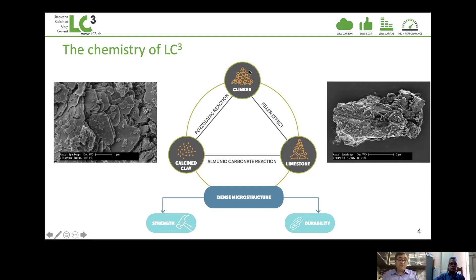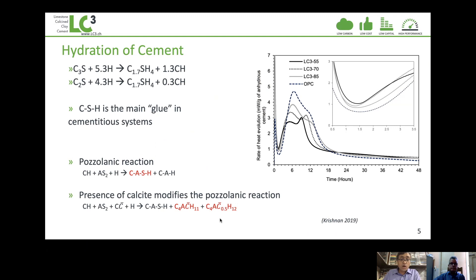This is despite having a lower clinker content. Whereas a Portland cement would have 90 to 95 percent clinker, and a fly ash-based pozzolanic cement would have 60 to 70 percent clinker, LC3 may have 50 percent or even less clinker and still achieve the same type of strength as other cements, at least in the long term.